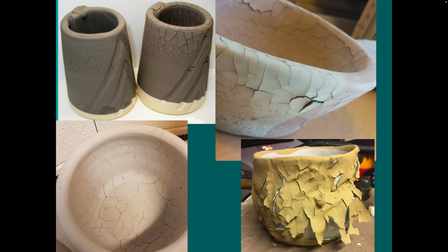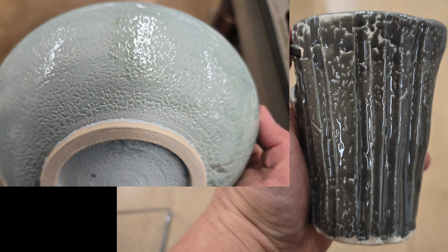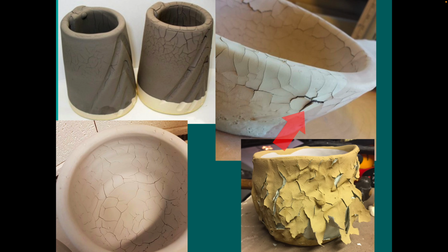And another issue that you may encounter is if you apply your glaze too thick, the glaze can crack and ultimately peel off. The pictures on the left show some light cracks, and as long as the cracks are not too deep, you can fire it without too many issues occurring. But if the cracks are a little deeper, like this piece here, when it's fired, the glaze may crawl away and leave naked spots like this. And as you move on to the pictures to the right, the top right is starting to lift up and peel away, and the bottom right is the extreme where that is done. There's no saving. You have to wash it, take off all the glaze, and reapply. And usually that happens when you overlap glazes.